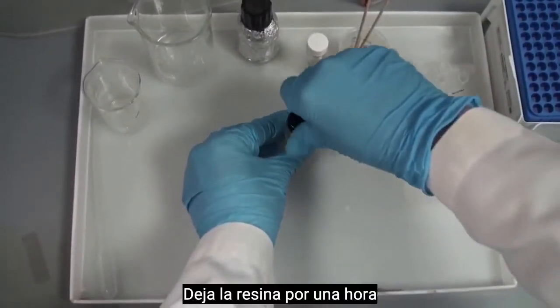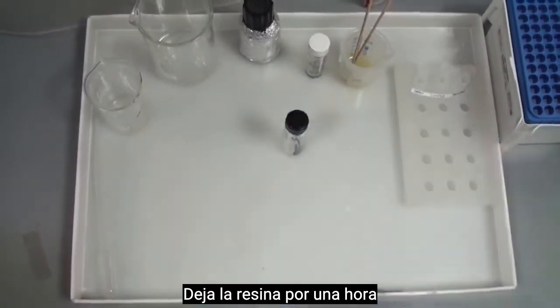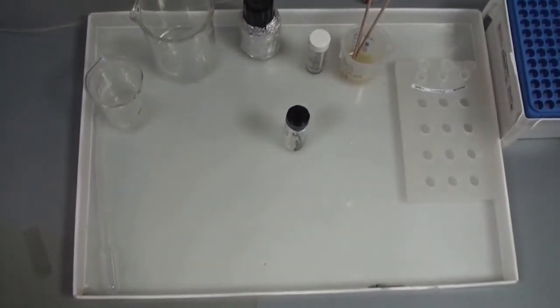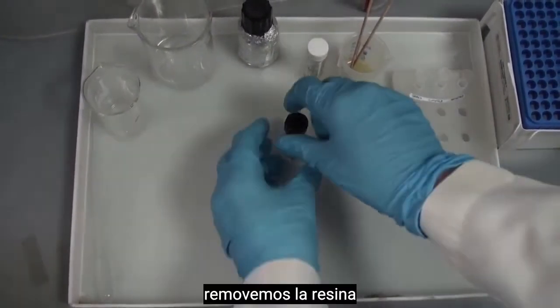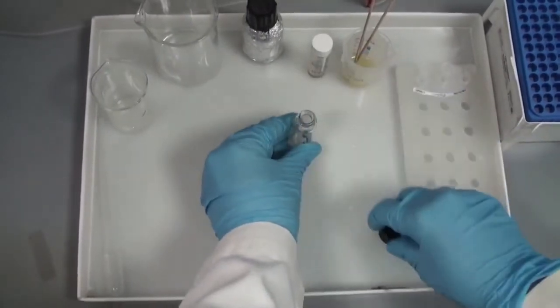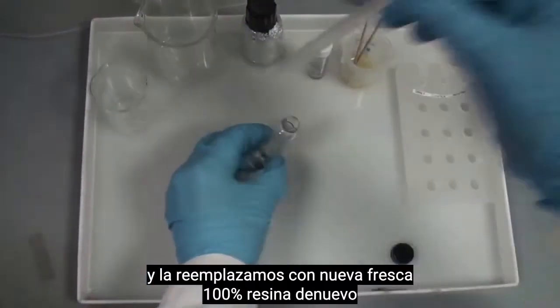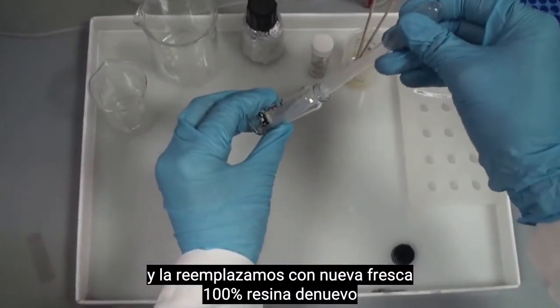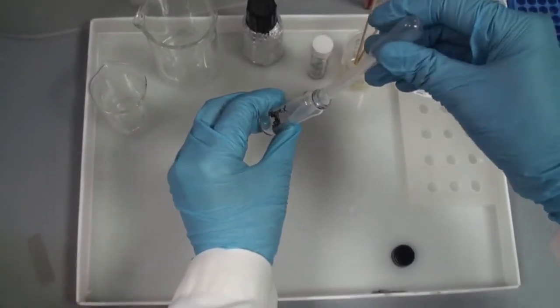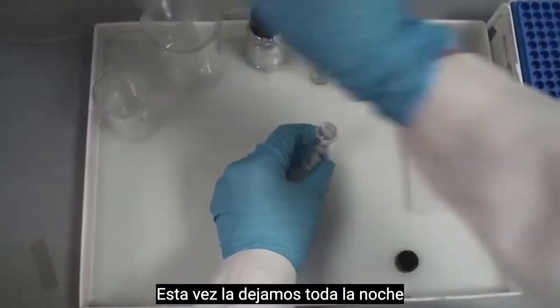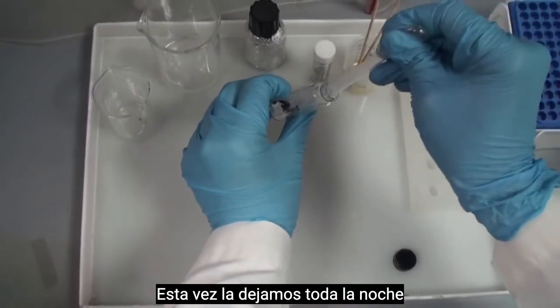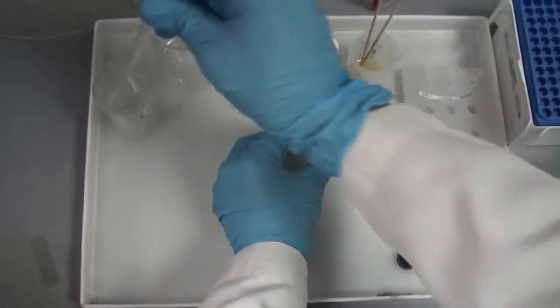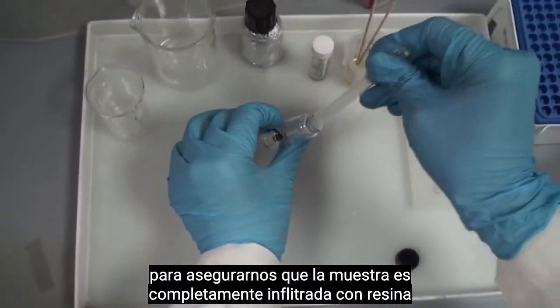Leave the resin for 1 hour, and after 1 hour we remove this resin and replace it with fresh 100% resin again. This time we leave it overnight to make sure that our sample is completely infiltrated with resin.